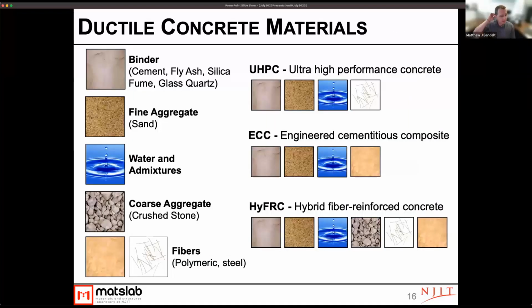So the different systems that we looked at in this project, again, were ultra high performance concrete, engineered cementitious composites, and hybrid fiber reinforced concretes. The UHPC system had a very high binder content, did not use coarse aggregate, and used steel fibers at a volume percentage of 2% by volume.